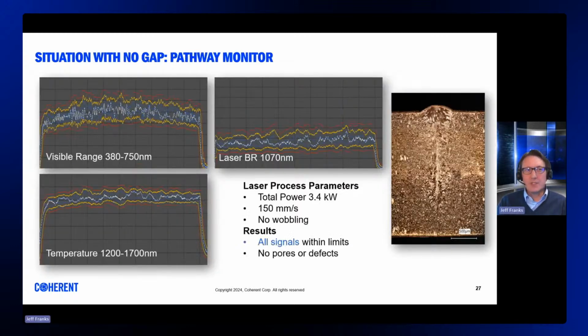Okay, we begin with a captured data set from a good setup with zero gap between the parts, and in this case, no dynamic beam movement, no wobbling. We can see how the white signal data stays well within the warning yellow bands and is generally even within the blue overlap good dataset. The resulting weld is clean and spatter-free and has a weld penetration of over 0.5 millimeter into the lower workpiece.